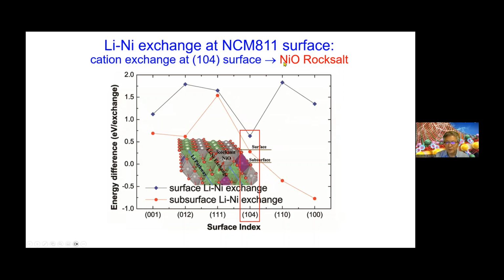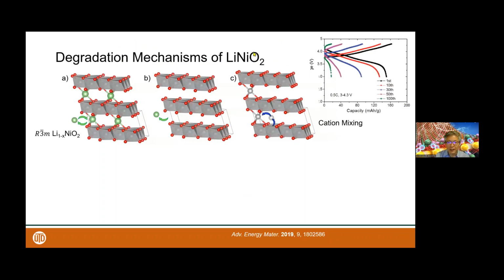But to form this rock salt phase, the surface metal atoms are moving, and you also need to adjust the stoichiometric ratio of this metal oxide to metal-oxygen 1:1 rather than 1:2. So you have to have oxygen loss, oxygen evolution. That's part of the degradation mechanism. The nickel-rich cathode material surface is behaving like a pure lithium nickel oxide.